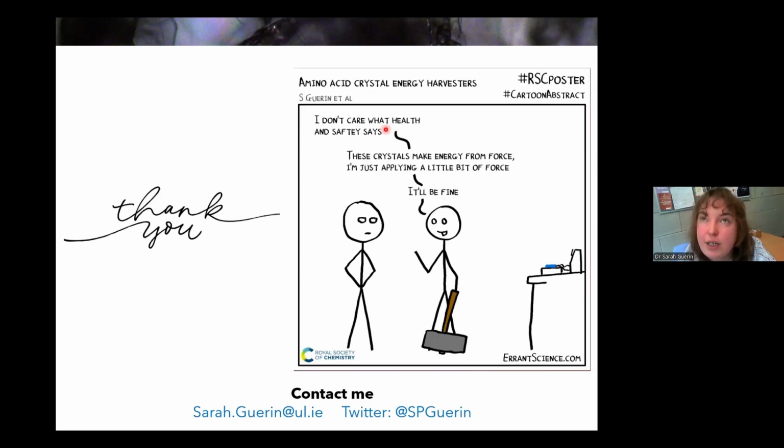Generally, we see them between about 1 and 5 gigapascals for a flexible material. And then our piezoelectric output is the ratio of the polarization to the stiffness. So if we have a monoclinic crystal, that tends towards having low C44, C55, C66, which means that our shear piezoelectric response will then be higher.